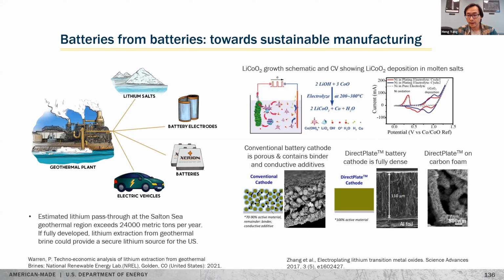And then on the right-hand side, this figure panel shows a few years ago, Xerion invented this direct plate technology, which is an electroplating technology from a molten salt environment. So we form a lithium cobalt oxide directly from molten salt on a conductive current collector. So this is fundamentally different than conventional battery electrode because conventional electrodes contain organic binder and conductive additives that are porous. In our case, it's monolithic, fully dense, so it can block the solvent molecules and only allow lithium ion to pass through. So we believe this structure aspect really makes it an excellent membrane material.